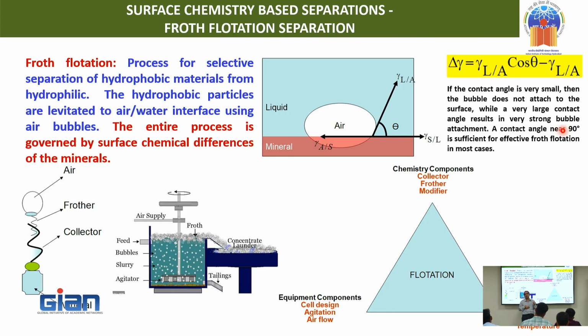Modifier also has some other effect. Suppose you have two sulfide minerals, right? You add some modifier, a metallic ion, so that one sulfide can be distinguished from the other sulfide. That is how you do the base metal separation. You add some copper. Copper itself can act as a modifier, some copper compounds like that. That copper will interact with sphalerite or galena or something, and it will nullify the sulfide surface. It will not allow the collector to adsorb on that, thereby allowing, among the two sulfide minerals, one to float and one to get depressed. So the modifiers can be inorganic molecules, they can be organic molecules, right? Doing all this type of action, that is, it modulates the flotation process. So these three, the chemistry part.